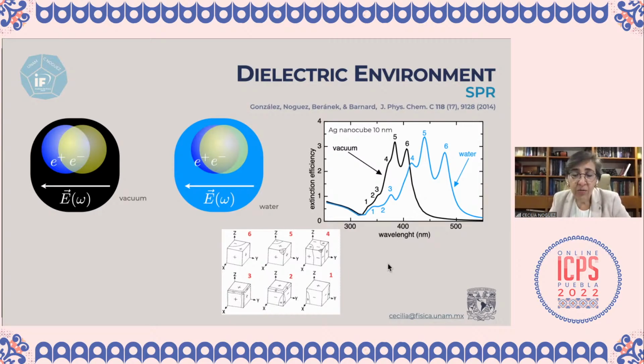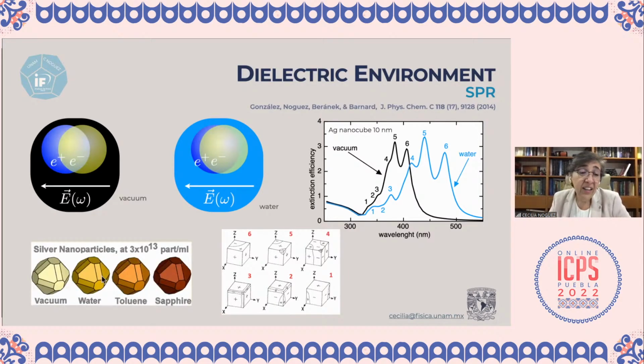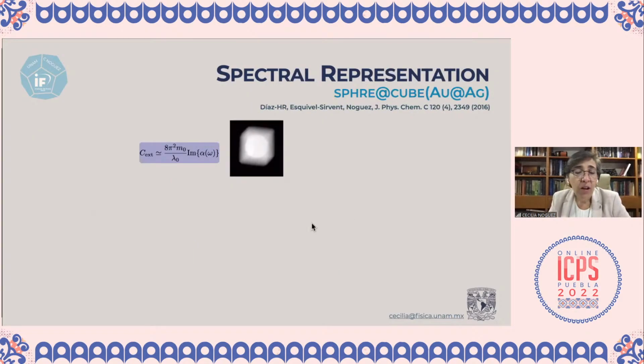Okay, so this is what happens when you have a different dielectric environment, and the solution will change in this transmission of light. The solution will change from, let's say, this color for this kind of shapes in the silver nanoparticles to this other color if the nanoparticle is immersed in, let's say, sapphire. Now, what we have done is to try to separate these contributions to the response of the nanoparticle. One is, as I said, the shape of the nanoparticle, and the other important contribution is where the nanoparticle is, and the second one is the material that composes the nanoparticle.